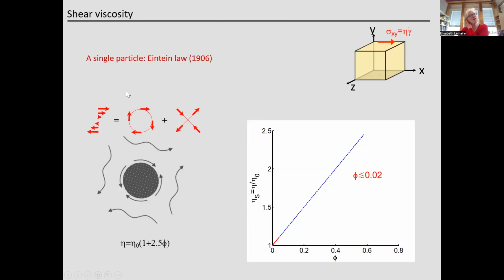So you know that if the concentration of the particles is very low, typically the particle volume fraction lower than 2%, then one particle does not see the other particles. And so to compute the viscosity, we just have to take into account the perturbation of the flow in the suspending liquid. And it's what has been done by Einstein to find this very famous law for the variation of the viscosity with the particle volume fraction.